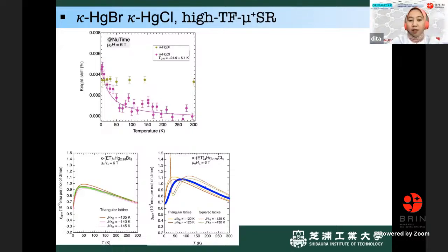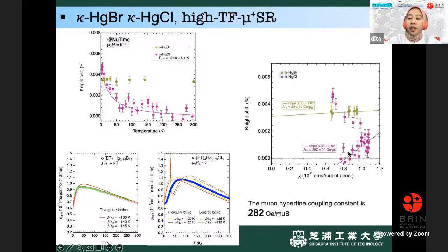So I will plot, at the same temperature, the Knight shift versus the susceptibility here. Okay, like this. For the bromine, we cannot see such an obvious difference. But for the chlorine, we can see a difference here, and we have deviations from the linearity. If we have the Fermi liquid situation, it will be only linear, but there is a deviation. So maybe this is related to the non-Fermi liquidity.